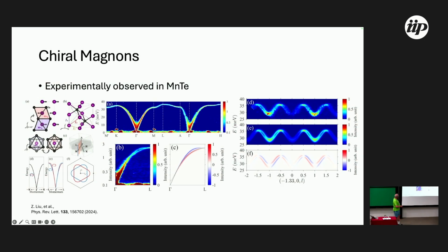Not all is lost, though. Here's another material, manganese telluride. Now, this is a little bit more complicated because it's not just cubic. The symmetries are slightly different. Here, if you look carefully enough, you do see this splitting of these two magnon modes, which theoretically should have different chiralities. From the inelastic neutron data, they can't tell the chirality of the magnon modes, but they see that there are two. So it's possible you have it in some materials, not in all. The details of the exchange interactions do matter there, I think. That's all I wanted to say about chiral magnons.